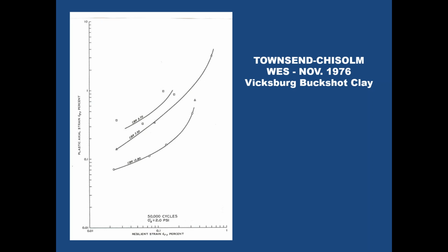Pueblo, in order to build a soft subgrade section. All they had was sand. And Ernie Seelig and I said, hey, we need to have a soft grade. So we got the railroads who were sponsoring the project to haul a lot of Vicksburg buckshot clay down to Pueblo. But as you can see, for particular resilient strain, depending on the strength of the subgrade, you got different values of permanent strain or permanent deformation that develop. So it says, hey, this doesn't work, but yet it's being utilized widely.